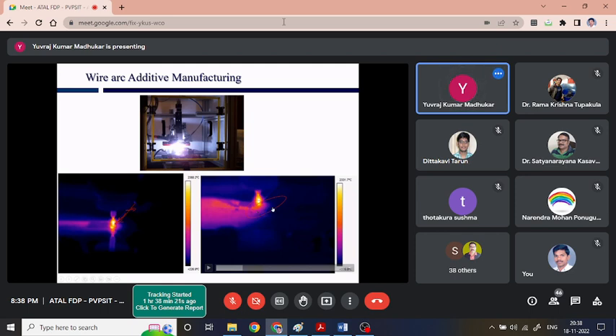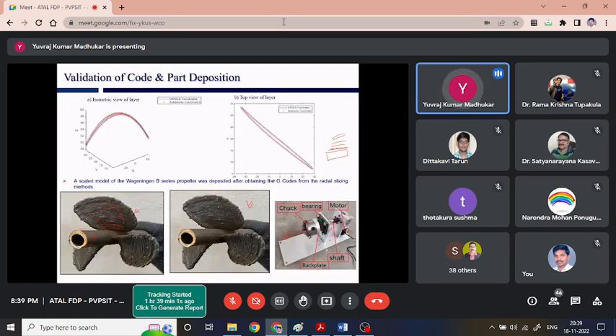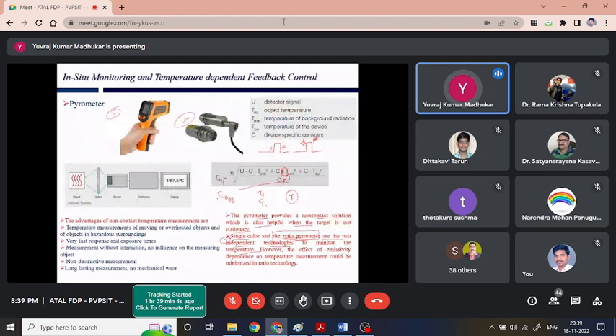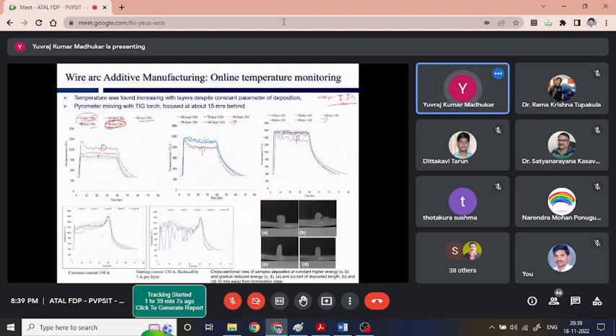It is because over the number of layers of deposition, we are adding mass to the system. Yes, that is true. However, the volume through which the heat has to pass is becoming much lesser, and this body is already at an elevated temperature. So despite giving some time interval between successive layers of deposition, it takes longer to cool down, which is reflected in a bigger melt pool size. That means with a lesser amount of energy, the same amount of deposition can take place, which was possibly happening over here.